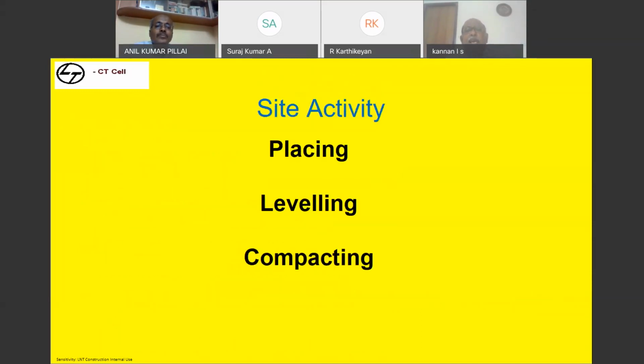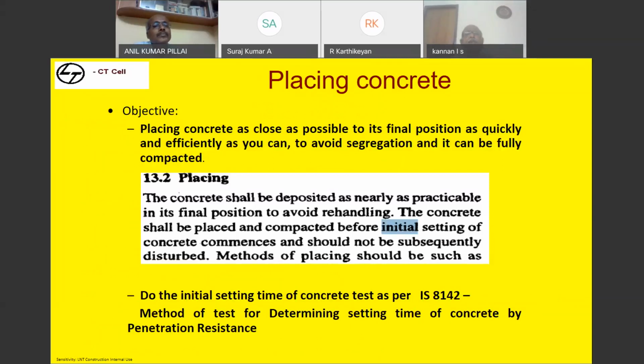Then it is coming to site activity. We are going with placing. Placing concrete as close as possible to its final position, as quickly and efficiently as you can, to avoid segregation, so that it can be compacted. So this is the objective. As per the code, the concrete shall be deposited as nearly as practicable in its final position to avoid rehandling. The concrete shall be placed and compacted before the initial setting time of concrete commences and should not be subsequently disturbed.